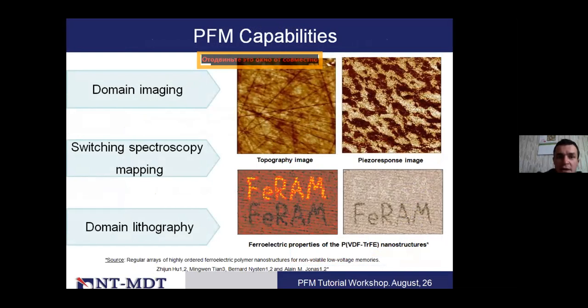Well, and here are some results. On the top, you can see the imaging of the topography of some piezoelectric film, and the piezoelectric properties on the right. You can see that they do not correlate with each other at all. So it means that it's definitely the piezo response effect. Also, if you have some domain structure, by applying different constant voltage between tip and sample, you can switch the piezoelectric domains. This is called domain lithography. You can see on the bottom two images that you can actually draw some pattern on the surface by switching the piezoelectric domains, and they will remain forever until you switch with the opposite voltage again.